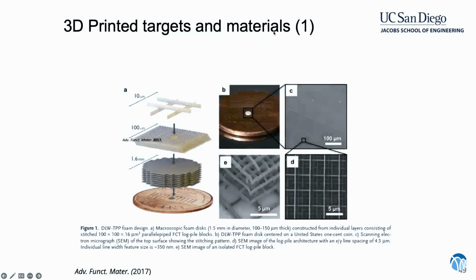So you can imagine as you start to make targets and fuel capsules designed for fusion energy, some of the choices you would make are what density of materials you would use and how they're structured. And I can show you a little bit more about this. These are some nice results out of Livermore in which they 3D printed targets. 3D printing, in this case two-photon polymerization, is very exciting because it might be a way that can be developed to print targets very quickly and very cheaply. What they were doing here is making a target that was a higher density on one side and a lower density on the other side, so they can get this increased ramp like I was talking about. And the way that this is architected has different scales.